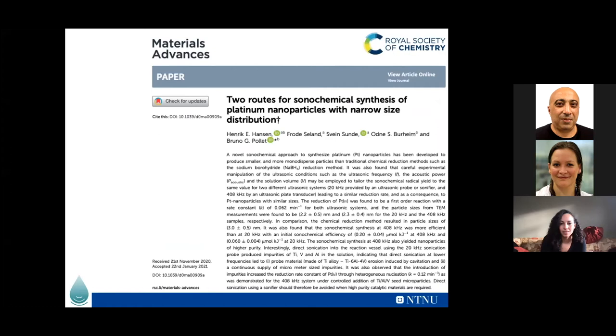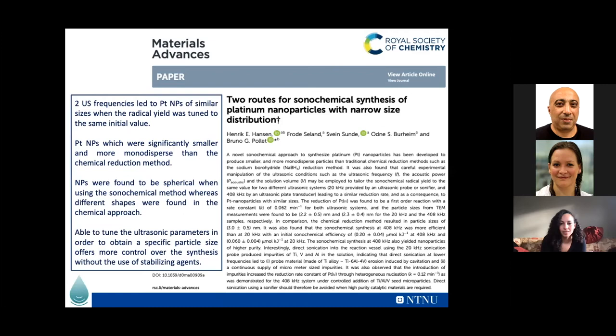And really that led us, a few years ago, to look at a system where we use two different ultrasonic systems. One was a bath, one was a probe, at different frequencies, one operating at 20 kilohertz and the other at 408 kilohertz. And what we found is that we were able to tune the ultrasonic parameters in order to obtain a specific particle size without the use of any stabilizing agent.